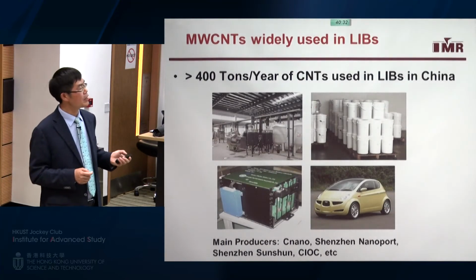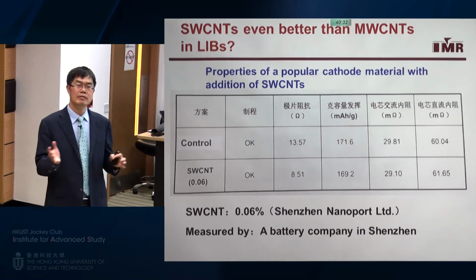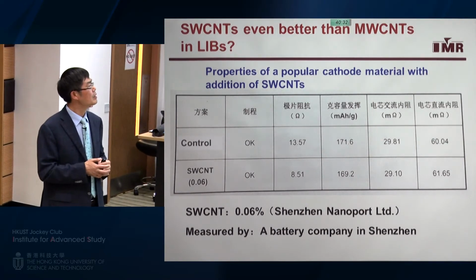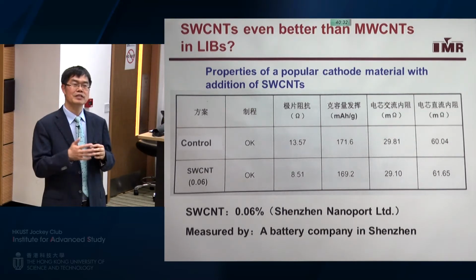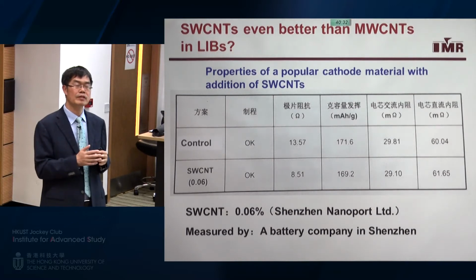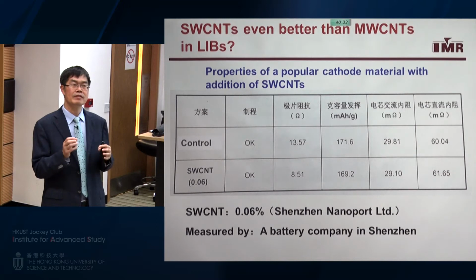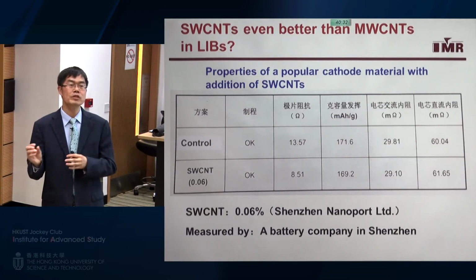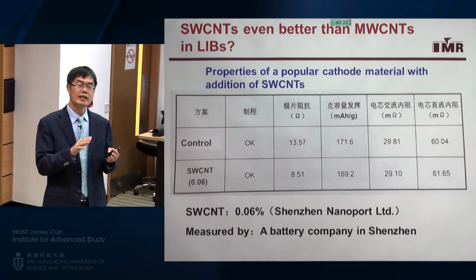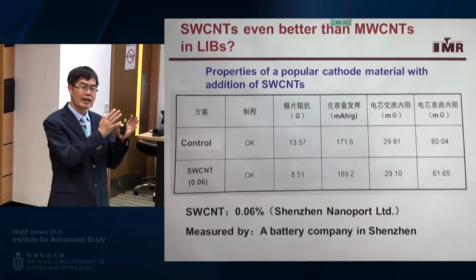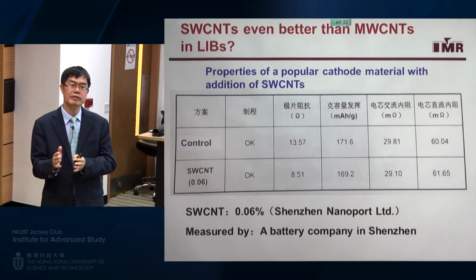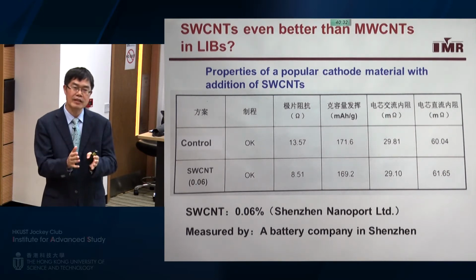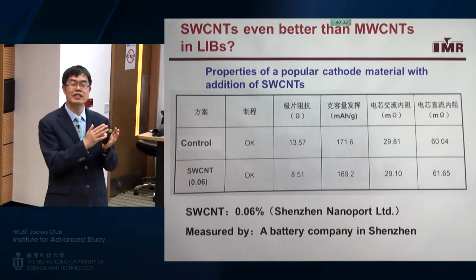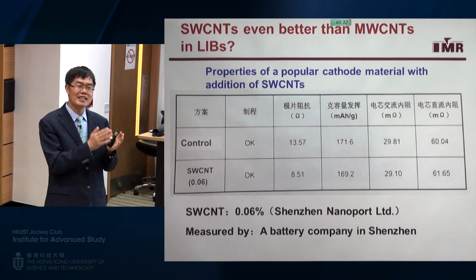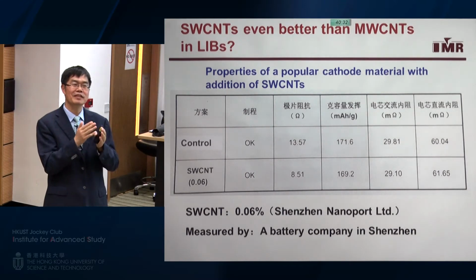Here we use multi-wall carbon nanotubes. Multi-wall carbon nanotubes have a very low cost compared to single-wall nanotubes. But we still want to use single-wall nanotubes because they have a very small diameter. If we use them, probably we can use a very small amount of single-wall nanotubes to replace a larger amount of multi-wall carbon nanotubes. In our battery, we have active cathode material, active anode material, a current collector, a separator, electrolyte, and also, as I just mentioned, additive and binder. Only the active materials contribute energy.